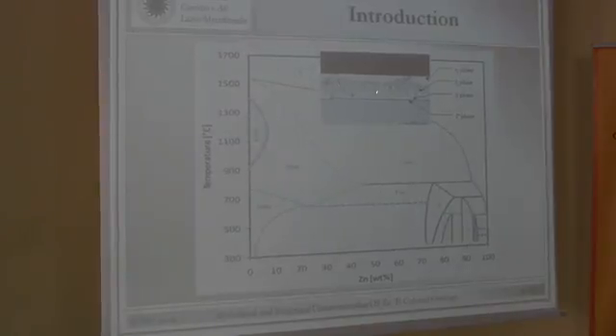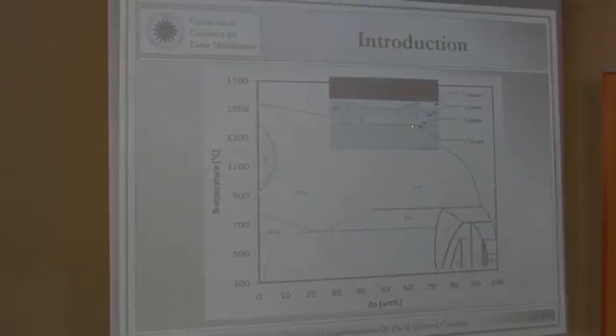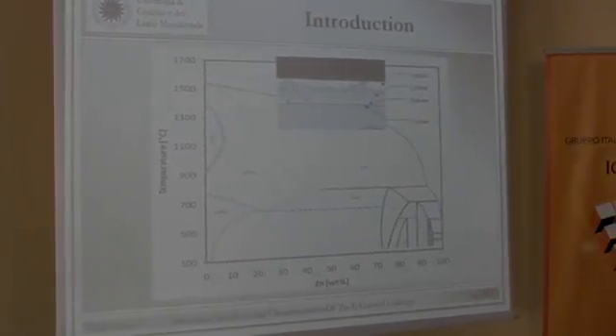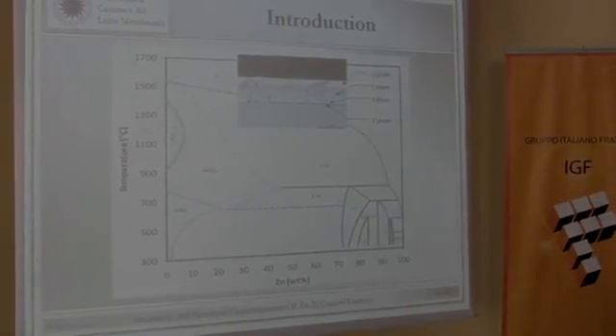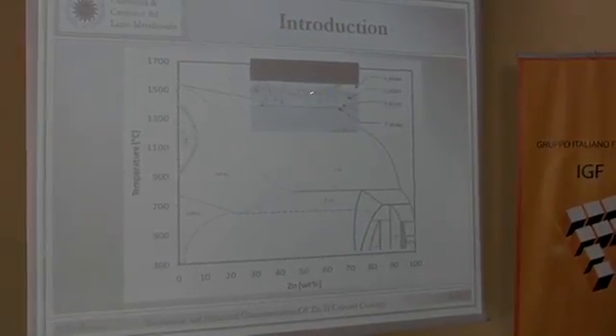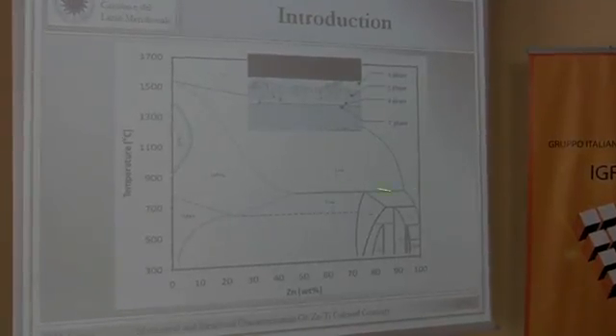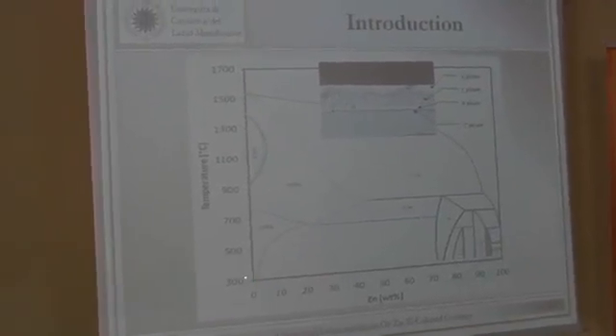This is a section of coating. We have different regions characterized by different chemical composition. In this zone, we have a much higher presence of iron. And in the outer zone, this is the surface, we have a presence of mainly zinc. In the intermediate zones, we have a presence of different intermediate phases. According to this diagram, we have presence of a brittle phase up to 18%